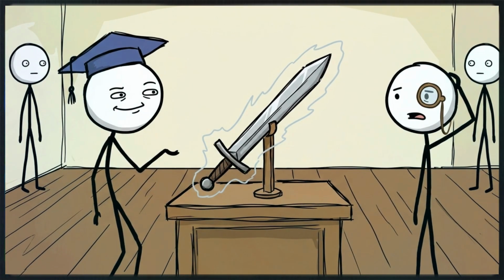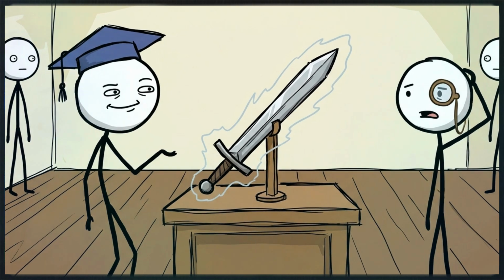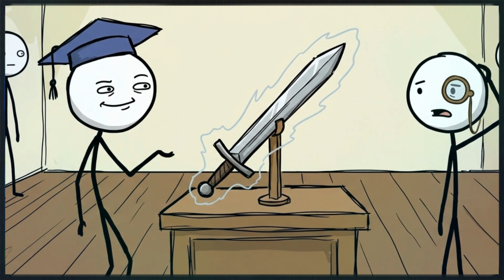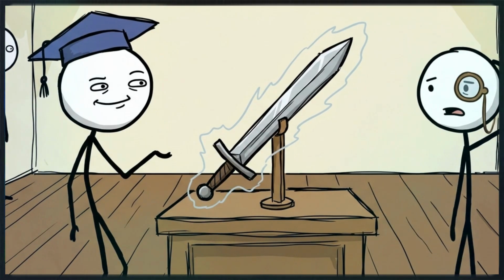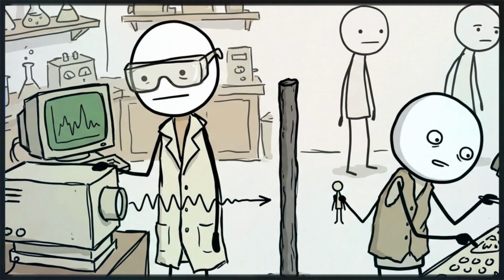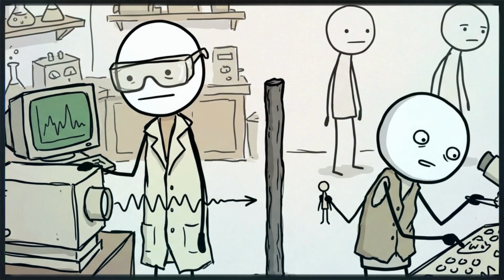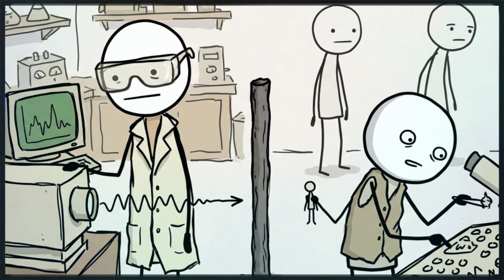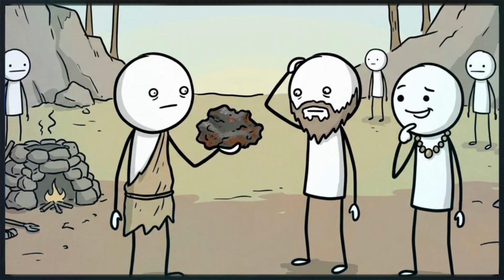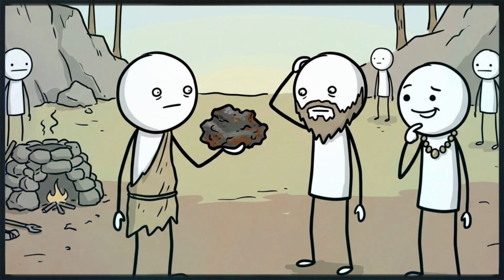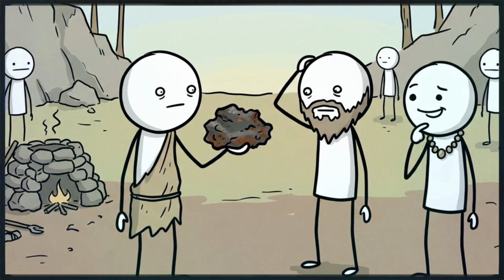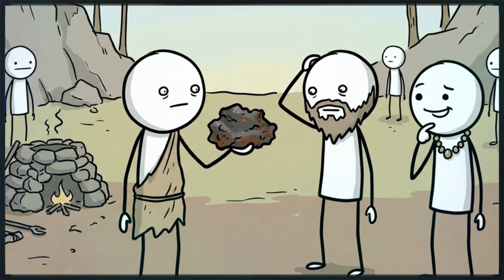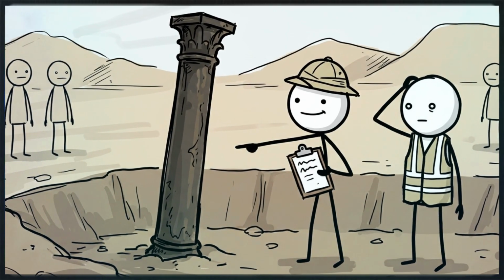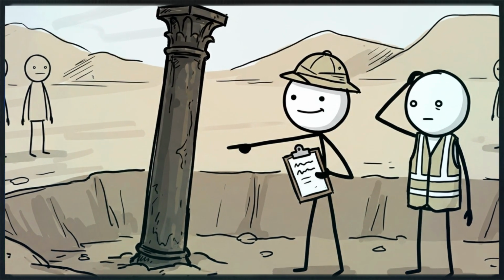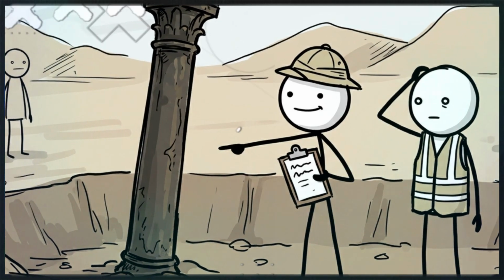Instead, it stands virtually unblemished, possessing an ultra-thin, invisible shield that completely halts the oxidation process. When modern metallurgists finally subjected the pillar to X-ray diffraction and electron microprobe analysis, they expected to find a primitive equivalent of modern stainless steel, perhaps an accidental alloy containing rust-resistant chromium or nickel. Instead, the results were baffling. The pillar is composed of 98% pure wrought iron.